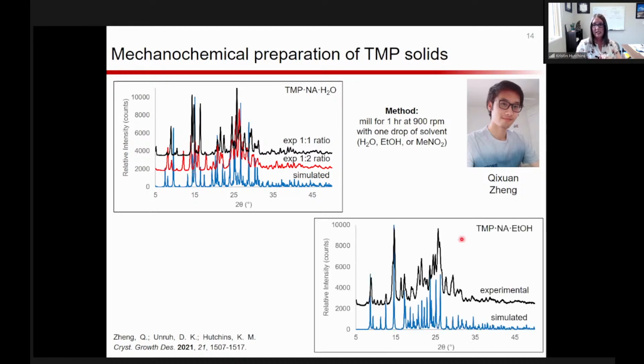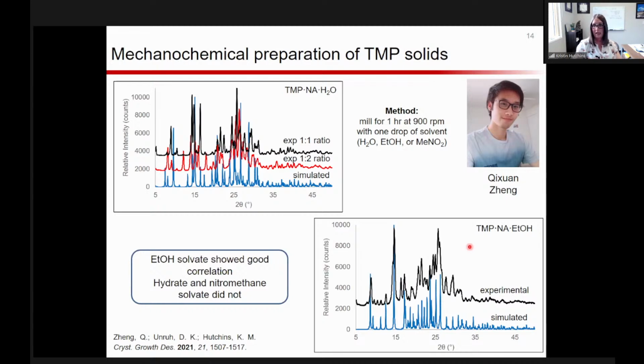On the other hand, in the case of the ethanol solvate, by milling we actually got really nice correlation to the simulated pattern. So with the ethanol solvate, we could make that via solution or by mechanochemistry. But with the hydrate, at least not without a little bit more optimization, with some of these quick and simple experiments, we weren't seeing really good correlation. And also the nitromethane solvate, we weren't able to get that by mechanochemistry. It probably showed the worst correlation of all three.